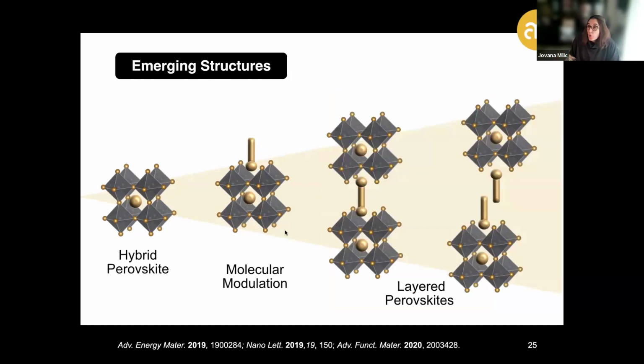This is done by building layered, or in this case two-dimensional, low-dimensional perovskite architectures, where the organic layer serves as a spacer templating the hybrid perovskite framework—either through monofunctional organic bilayers known as Ruddlesden-Popper phases, much more conventional for layered hybrid perovskite systems, leading to a half unit cell offset between the inorganic slabs, or through a bifunctional organic monolayer forming so-called Dion-Jacobson phases with well-aligned perovskite slabs.